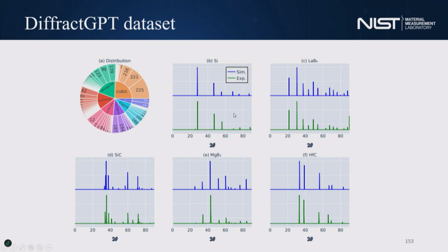And to my knowledge, XRD is the only method, at least powder X-ray diffraction, that can be easily calculated just from the POSCAR file. I don't think there's any other experimental method, whether it's Raman, neutron scattering, or ellipsometry, where you don't still need to do some field calculation or DFT calculation. But XRD is probably the only method that doesn't require any subsequent calculation.